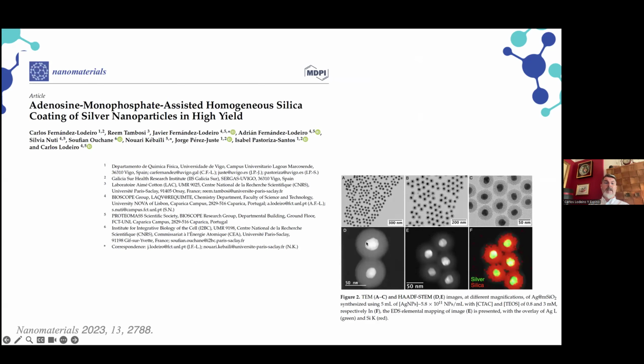These nanourchins have been protected with an external silica coating shell in order to reduce the release rate of the silver ions. You know that one of the antimicrobial effects of the silver nanoparticles is because of the silver ions released to the medium. However, many of these nanoparticles are easily hydrolyzed, are very unstable in a water medium, so you need to control the release of the silver ions. In that case, just putting a silica layer around the nanoparticle, and you play with the length and the thickness of the silica layer, you can reduce the release, and then the nanoparticles last a long time for the biological or macrobiological applications.